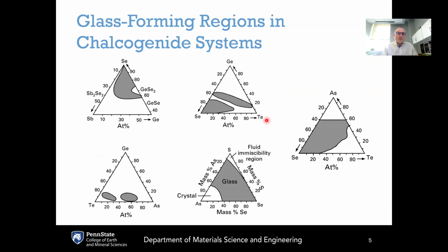In terms of the glass forming regions, the guiding principle is really Phillips's constraint theory and trying to design the glass composition to be near that isostatic region where the number of constraints is equal to the number of degrees of freedom. That being said, you can still form glasses across a pretty wide range of compositions in the under-constrained and even a bit into the over-constrained regions.